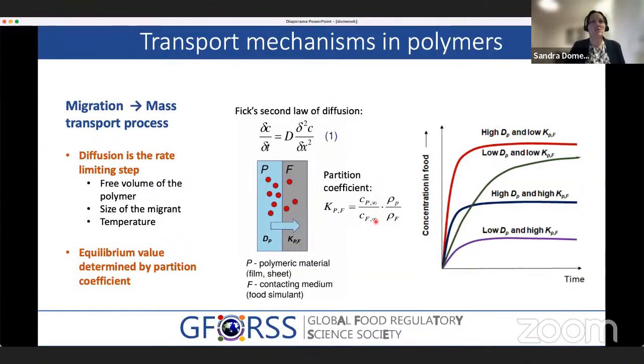This is a convention, so this is describing how much of your contaminant is going to be dissolved in the food at the end of the equilibration process, with respect to the part which is remaining inside the polymer. The fact that it is termed like this means that when the value here is high, then you are on the good side, which means that the contaminant very much likes the polymer and doesn't like the food. So this is good.